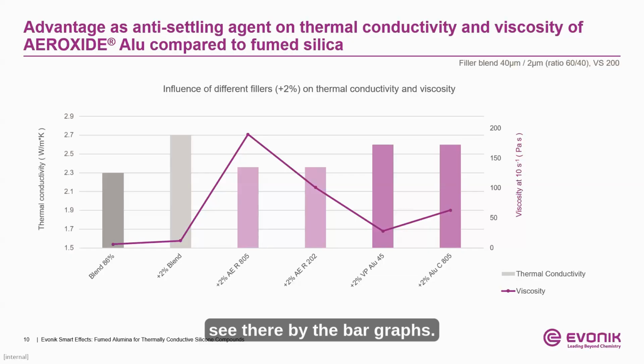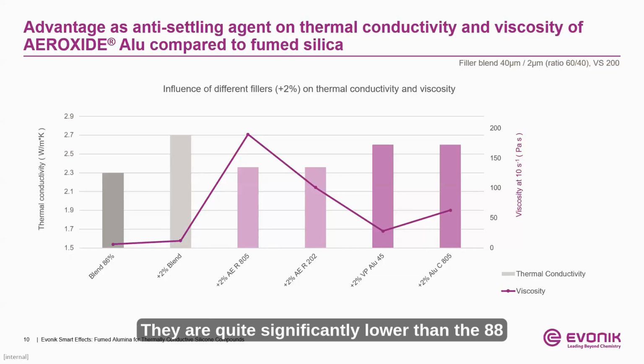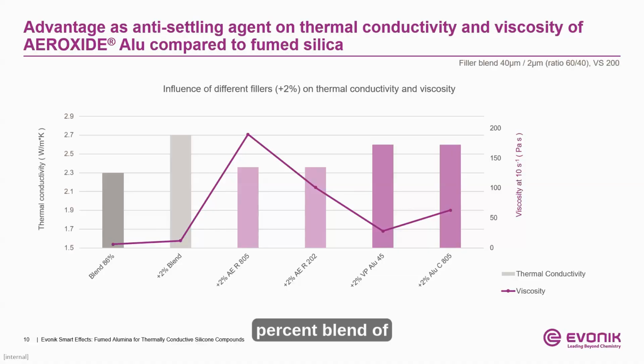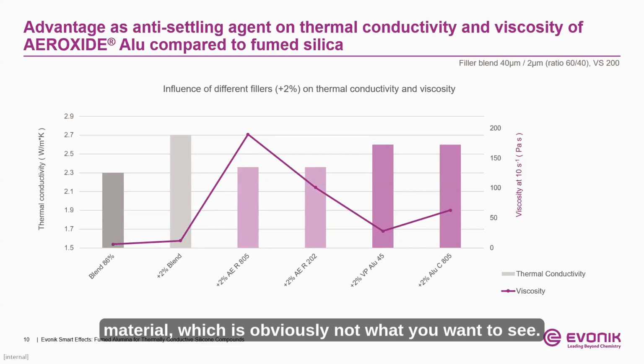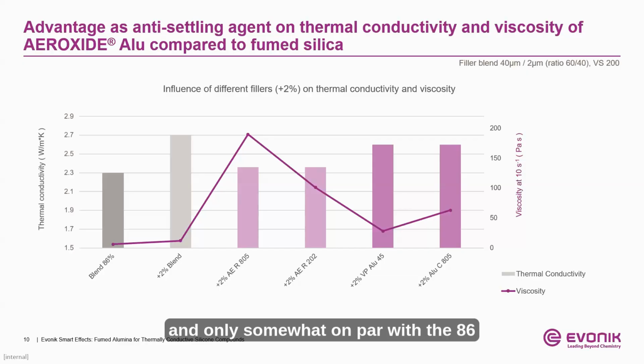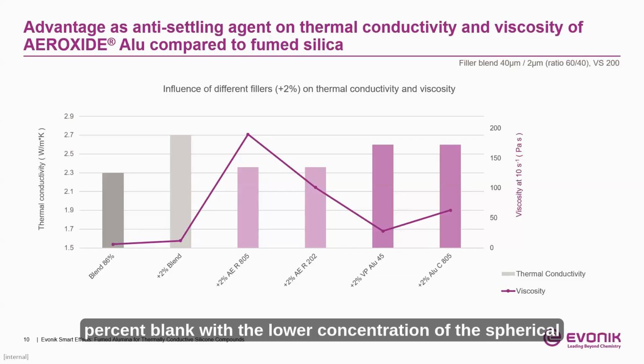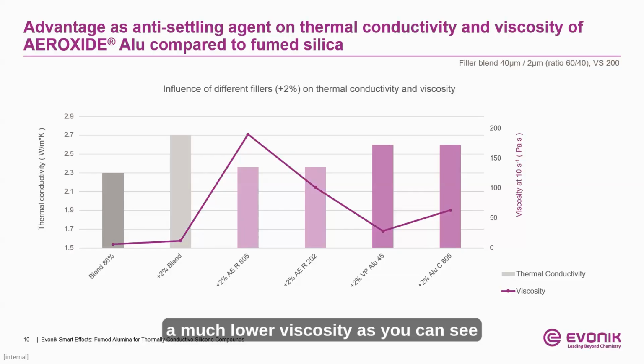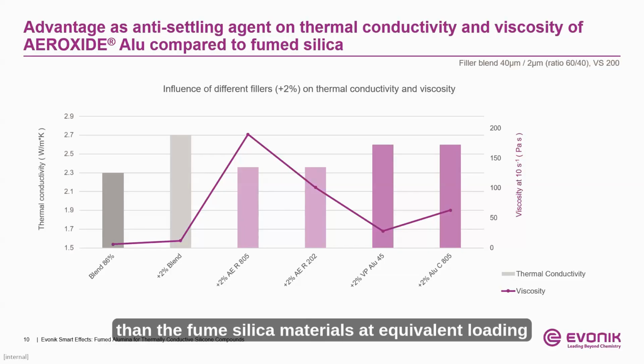As you can see there by the bar graphs, they are quite significantly lower than the 88% blend of material, which is obviously not what you want to see in these highly thermally conductive systems, and only somewhat on par with the 86% blend with the lower concentration of the spherical alumina. However, when we evaluate the fumed alumina samples, we first notice a much more manageable viscosity, a much lower viscosity, as you can see here, than the fumed silica materials at equivalent loading levels.